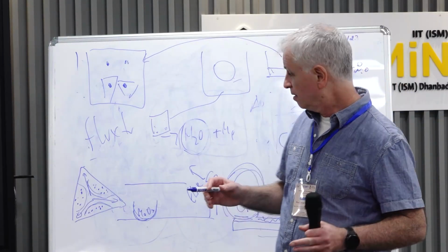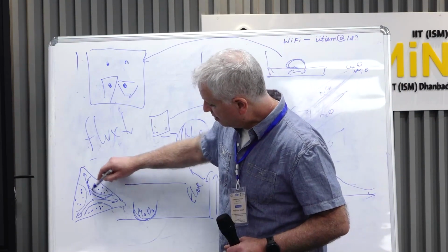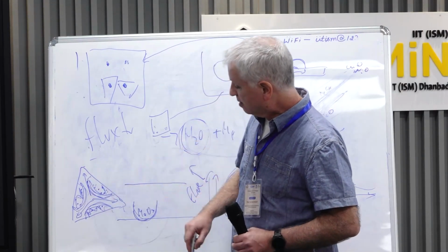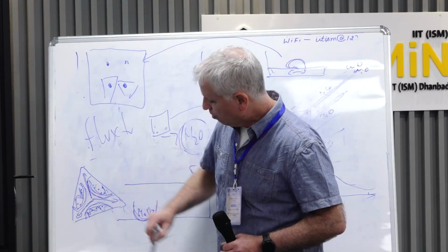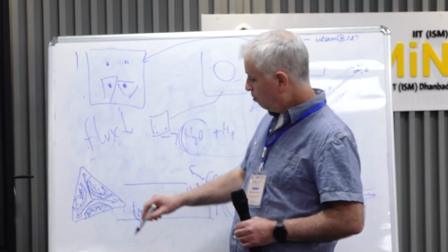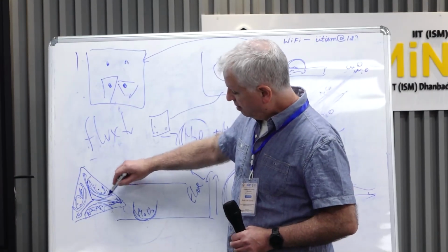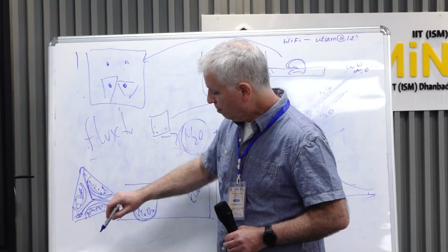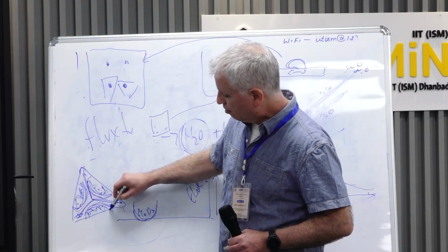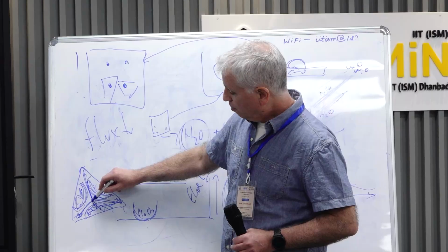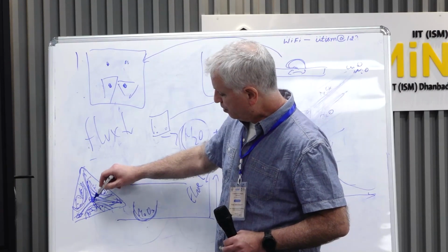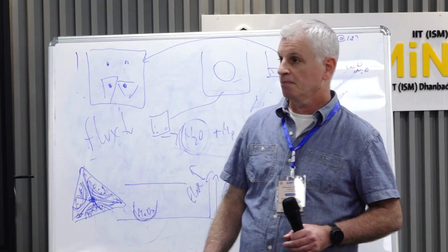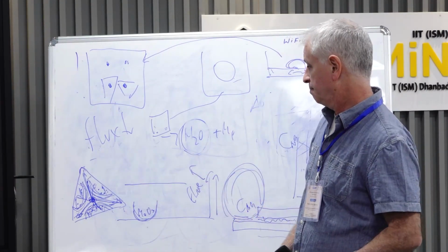Small concentrations, but gold only in these areas. And why in these areas? We assume it is because these directions grow faster. So we believe that first these corners grow, and then the rest is incorporated, and by then we have enough time and temperature for the gold to diffuse only to these areas and to grow with the material.